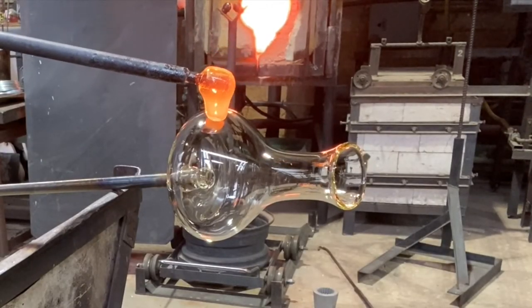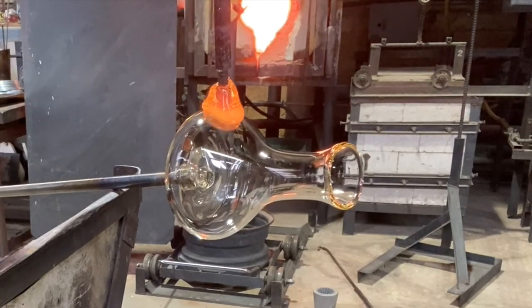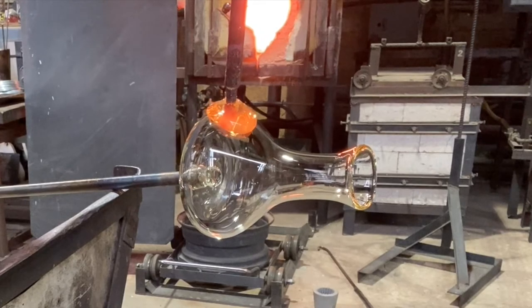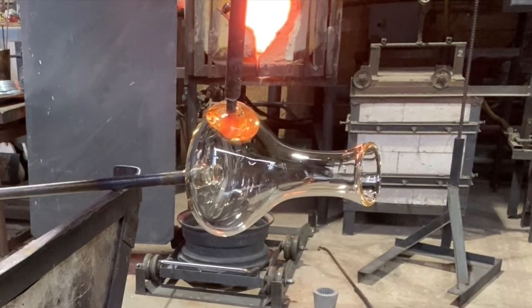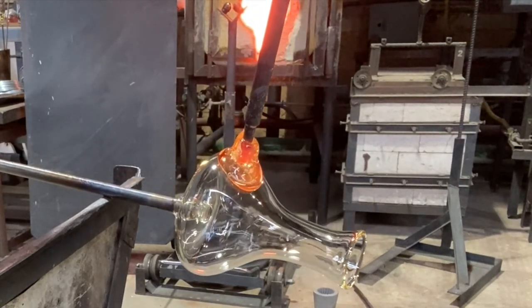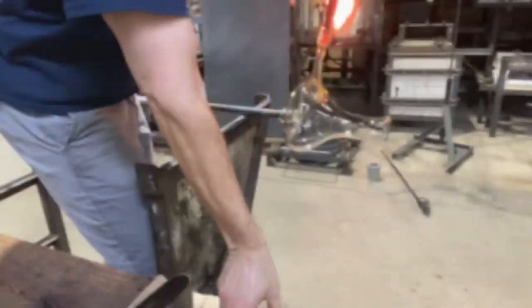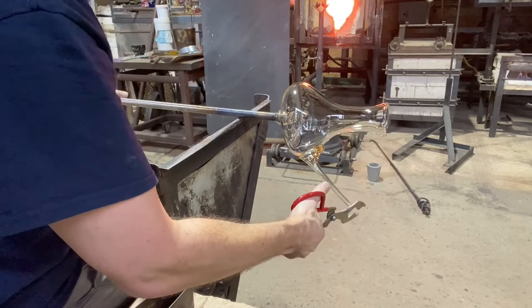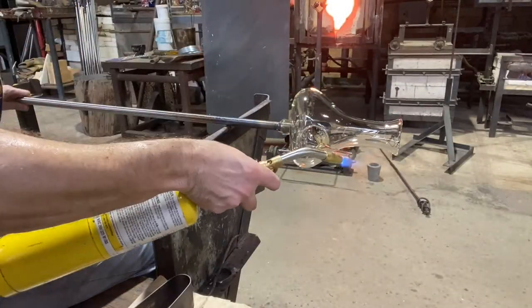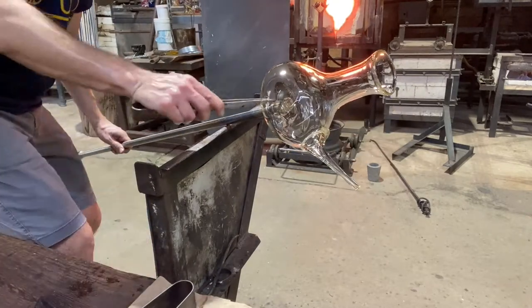So in slow motion, you get glass fresh from the furnace and put it on the side where you want the spout to be. Then I'll turn this punty up and push through the wall — or into the wall — of the vessel. You'll start to see that hot tip of the punty go into it, right there, kind of going through the wall. Now I know I've made it in, and I'm going to slowly pull it out. It's the extra glass that I pushed into the wall of the vessel that I'm pulling out — that makes the spout. Because I'm pulling out, that's hollow now, since I grabbed that glass from the vessel side. So it's a hollow spout. Now you've got to shape the spout and you don't have a lot of time to do this. Right now the spout is closed off, so I'm squeezing right there to knock the closed end off without closing it up. I'll fire polish it so no one cuts themselves when they drink out of it. And there we go — that last piece was the spout.